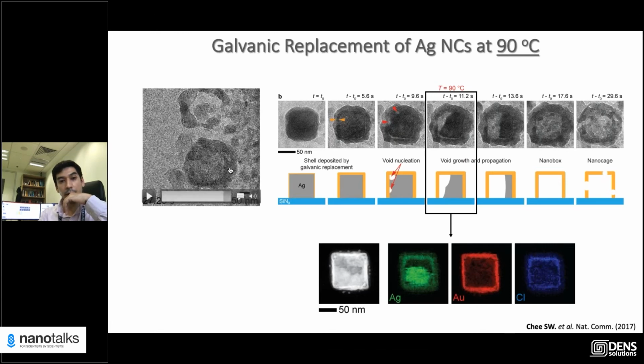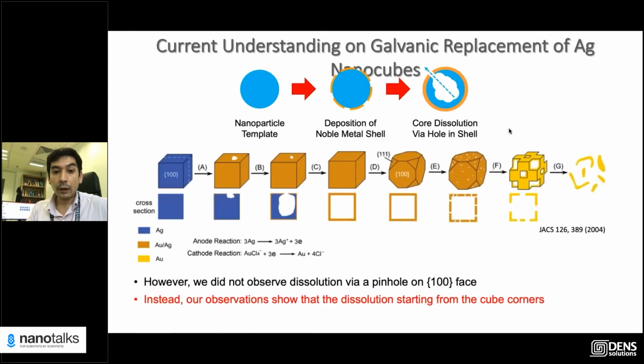How can we be confident that there is no hole forming? Okay, so this reaction was done at 90 degrees, right? And it proceeds quite fast, and we don't know what's happening. But one thing that you should know from the earlier part of my talk, where I described the Kirkendall effect, is that you might want to consider that there might be an interdiffusion happening at this interface between the two metals, and that's going to be the key message of this observation.